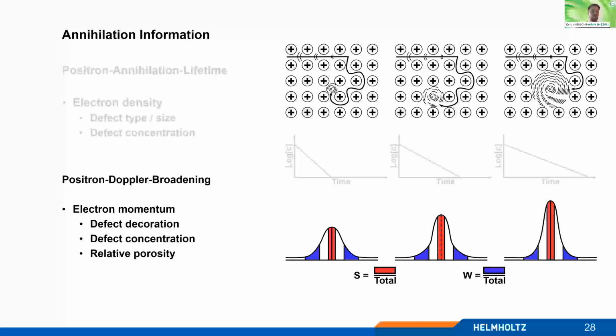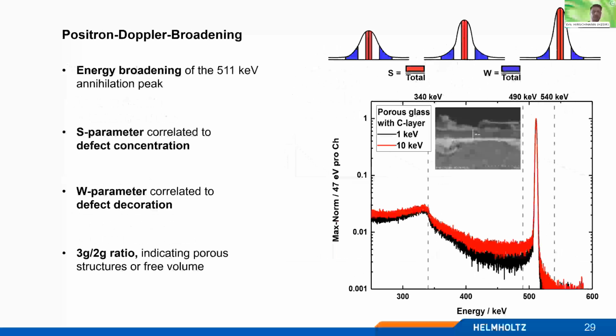This is called positron Doppler broadening, which measures the annihilation spectrum, so the energy spectrum of the annihilation event. This can be used to investigate the electron momentum transferred to the gamma release during the annihilation event. And this leads to some information about the defect decoration, defect concentration, or the relative porosity. As you can see here, this is the energy spectrum for this kind of Doppler broadening measurement.